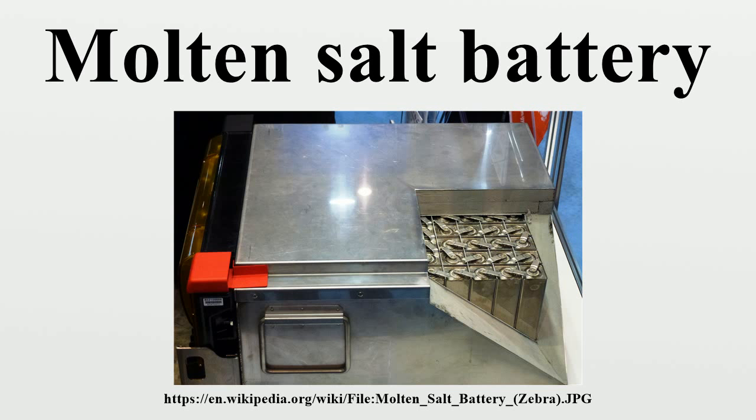The standard heat source typically consists of mixtures of iron powder and potassium perchlorate in weight ratios of 88:12, 86:14, or 84:16. The higher the potassium perchlorate level, the higher the heat output.